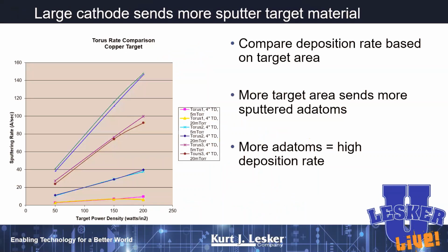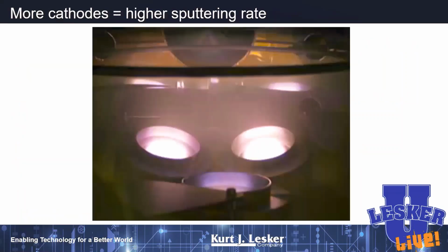Now, if you're dialed into throw or deposition rate, the other thing you can do is increase the size of your cathode. So if we go from a 1 inch to a 2 inch to a 3 inch to a 4 inch cathode, we can dramatically increase the number of atoms that we're throwing at any given substrate per unit of time, and that will increase your deposition rate. It's a little expensive way to go. We can also increase the number of cathodes. If you really have to have a higher deposition rate, instead of sputtering from 1 cathode, add 2 or 3 cathodes, and point them all at your substrate up here, and you can increase your deposition rate that way. So again, these are all tricks that you can use to increase deposition rate.